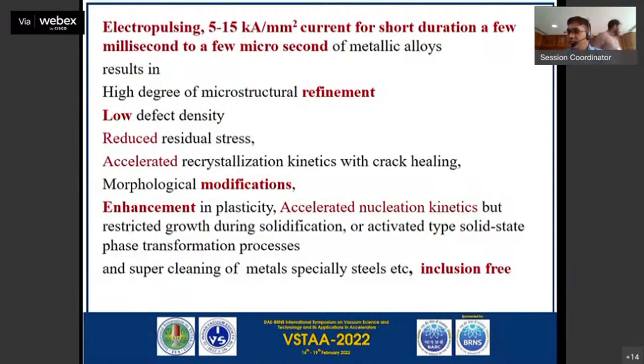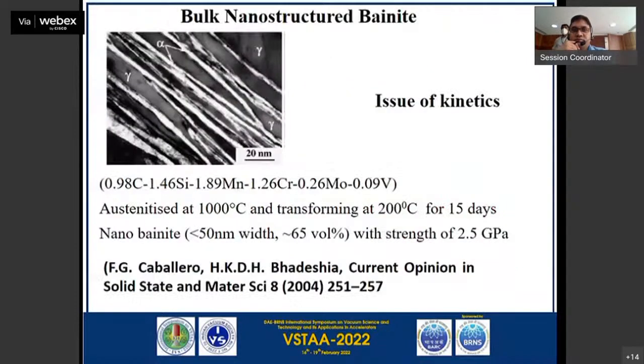Bulk electropulsing can be used for grain refinement, low defect density, reduced residual stress, accelerated recrystallization kinetics, and especially accelerated transformation kinetics. Next slide, please. Bulk nanostructured bainitic steel was developed by Professor H.K.D.H. Bhadeshia at the University of Cambridge. Now here the material has very good mechanical properties, but the transformation kinetics is very low.